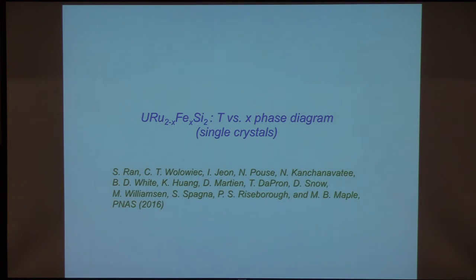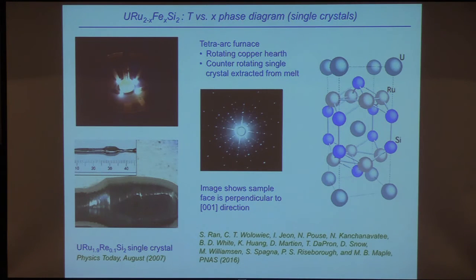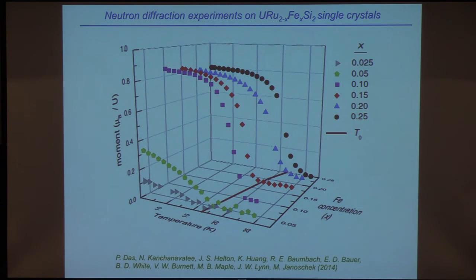So we've now spent many years growing single crystals, and so I won't bother you with the details, but there's such a single crystal. And what we found is that if you now do neutron diffraction, so here's magnetic moment versus temperature at various iron concentrations, increasing in this direction, then you start out with a low moment. The moment increases up to, in this case, about 0.8 Bohr magnetons, and then thereafter it decreases slowly. So we believe that this is the hidden order region right in here that you can now transform into large moment antiferromagnetism as a function of iron concentration.